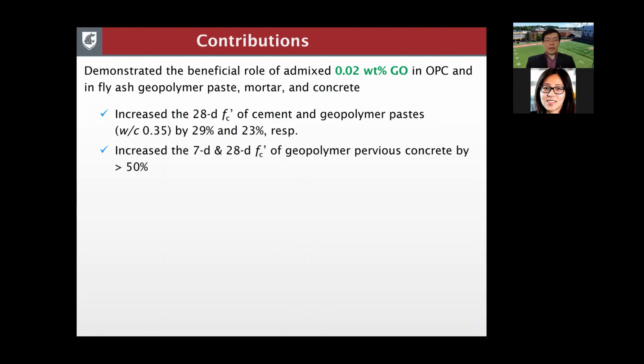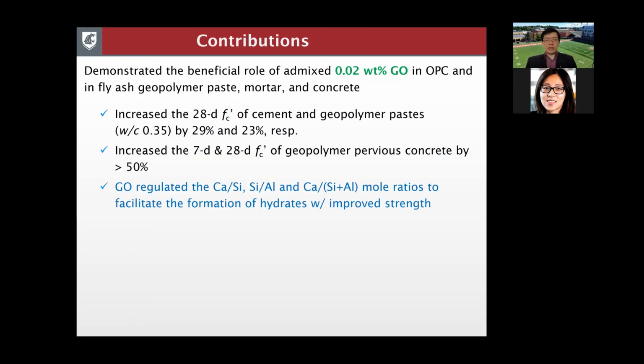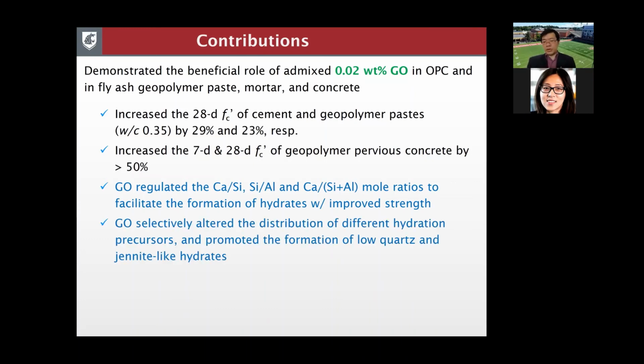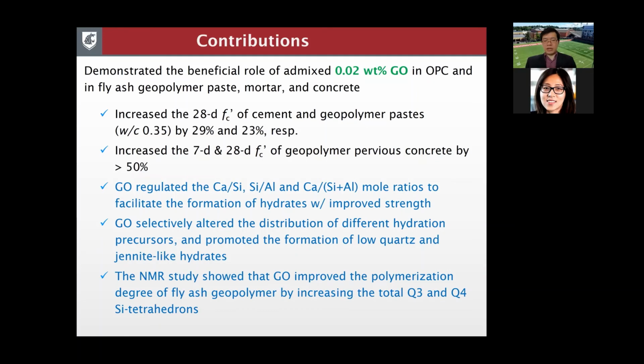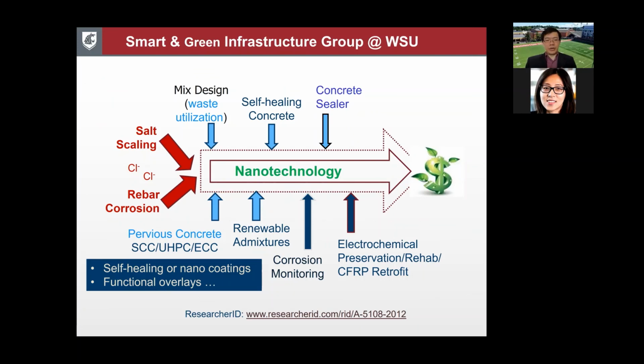And for the geopolymer concrete, the benefit was much larger. The 7-day and 28-day compressive strength had a larger than 50% increase. And GO regulated the molar ratios of these network formers, network intermediates, and so on, to form a different type of hydrate with improved strength. And GO selectively altered the distribution of different hydration precursors and promoted the growth of low quartz and jennite-like hydrates. And the NMR study showed GO improved the polymerization degree of fly ash geopolymer by increasing the total amount of Q3, Q4 silicates.